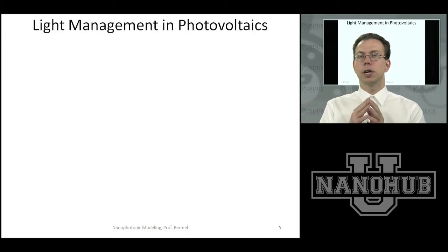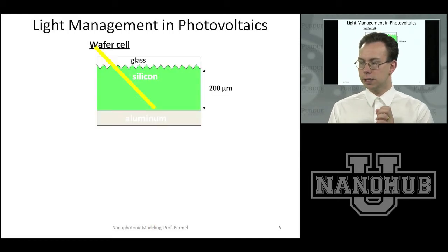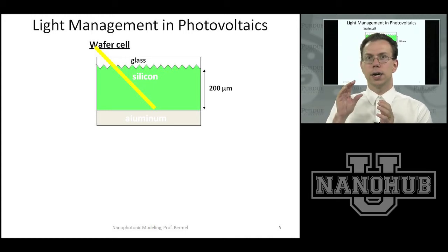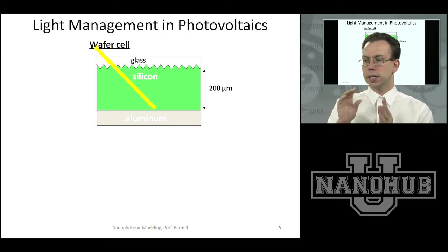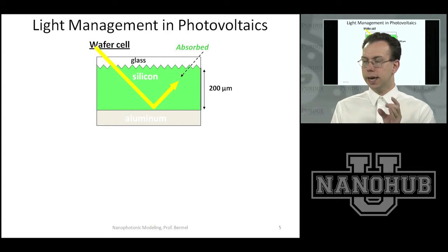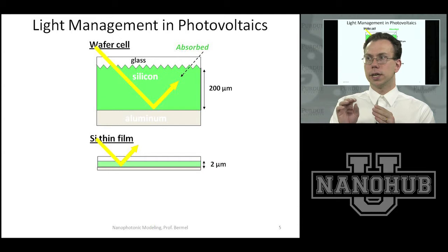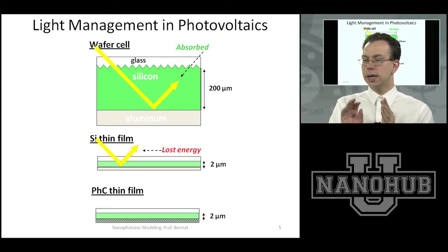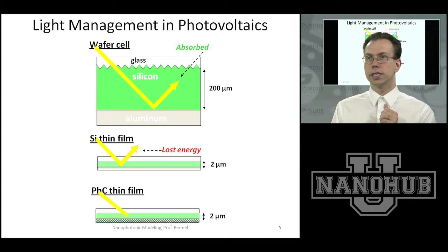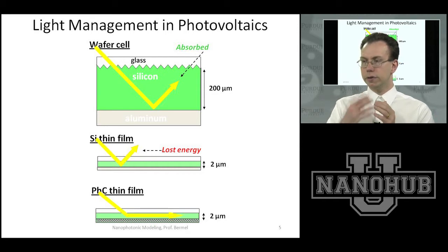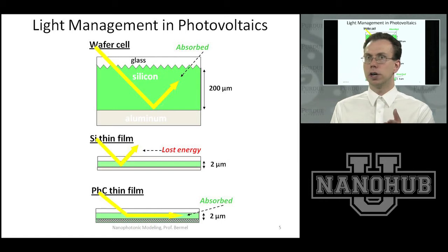Let me give you an example of why light management in photovoltaics is so important. A wafer-based silicon solar cell is typically very thick, on the order of 200 microns, which actually uses more silicon than the electronics industry today. That's enough to fully absorb the incoming light. However, if you try to reduce silicon usage — since silicon is expensive to purify — then there's not enough silicon to fully absorb light, especially in the infrared, degrading the efficiency of silicon thin-film solar cells. But if you introduce a photonic crystal-based thin-film structure on the back, that allows you to send light into so-called waveguided modes where it can be more fully absorbed. This work was recently published in collaboration with Minghao Qi, also at Purdue.